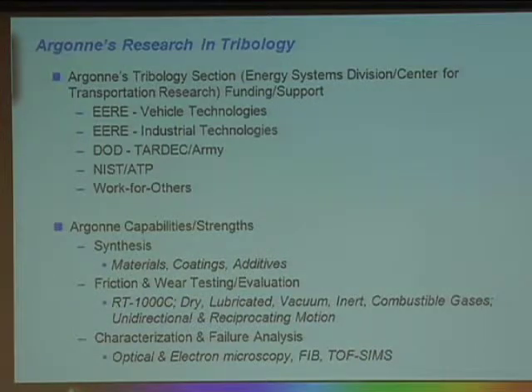In terms of Argonne's strengths and capabilities, what we bring to the table is work in synthesis, the development of advanced materials, coatings, and additives. Also work on friction and wear testing and evaluation. Once you develop these advanced materials and coatings, how do they perform relative to other materials that are typically used? We test components at temperatures ranging from room temperature to 1,000 degrees C, under either dry, lubricated, vacuum, inert gases, or actually combustible gases, in a couple of different reciprocating modes or unidirectional sliding.